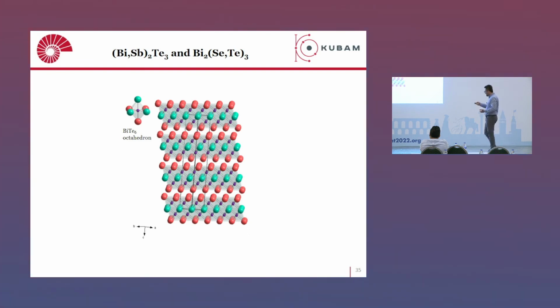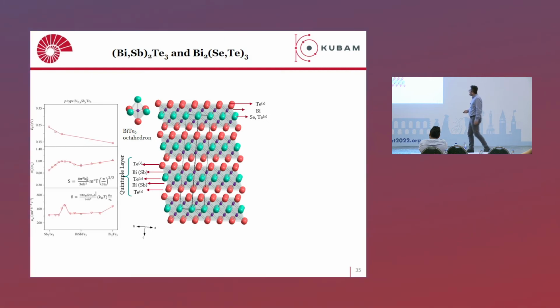So here is the unique crystal structure of this. So we see in this crystal structure these layers of bismuth telluride, which are called quintuple layers. So here in the microstructure, you can see that in the crystal structure, we have these bismuth atoms octahedrally coordinated with the selenium, with the tellurium. And you can see that if you just do a solid solution of bismuth telluride with antimony telluride, you can also engineer the mobility, effective mass, and the band gap. And we just focused on these two materials. One is with bismuth 0.3 and the other one is bismuth 0.5.